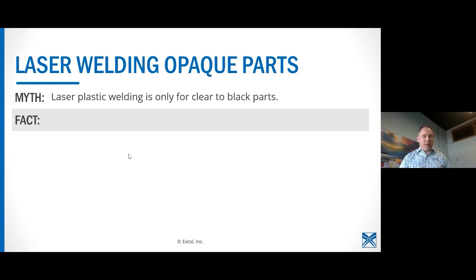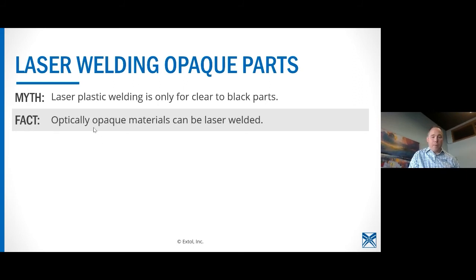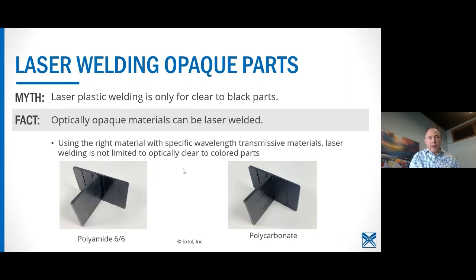So opaque parts, laser welding is only for clear to black, right? The fact is, optically opaque materials can be laser plastic welded. These are 2 really good examples from one of our step plaques that we can mold for you, either with your own material if you're a customer, or we can work with the resin supplier to dial those in. And essentially what's happening here is optically they look opaque, but the infrared wavelength that we're using for our laser is transmissive. So you can see that polyamide 6.6 there, and this is I want to say 1.5 millimeters thick. We can go all the way to 2.5, and polycarbonate, both laser plastic welded, and you can see the flash on the side is very, very narrow on that. So quite robust. We've got a laser inspection system, optical system, and you can see right through it as if it's clear as can be.